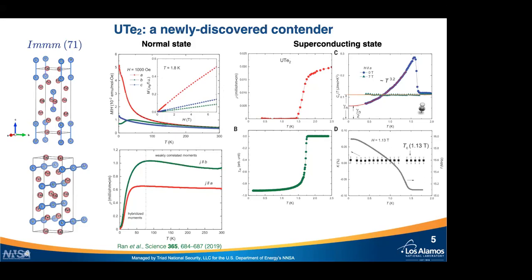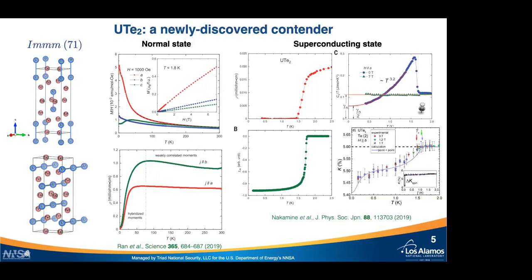Finally, NMR, or nuclear magnetic resonance on tellurium, shows almost no Knight shift through TC. And just recalling that if we have a spin singlet material, the Knight shift has to go to zero at zero temperature. If we have a spin triplet superconductor, we wouldn't expect a very large change at TC, and that's exactly what's seen. Though I need to point out that those first experiments were done in powdered samples,